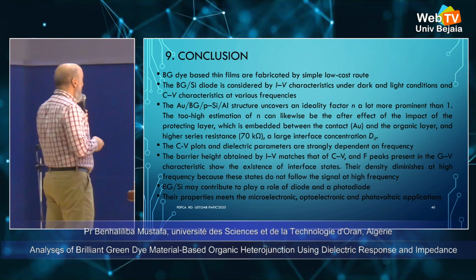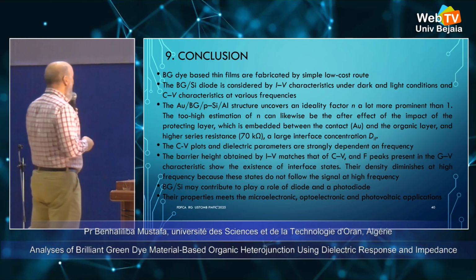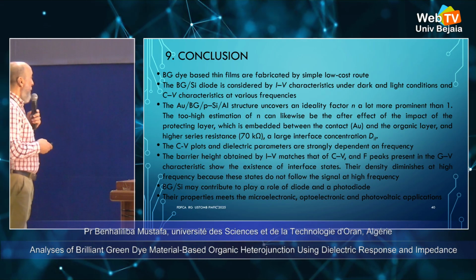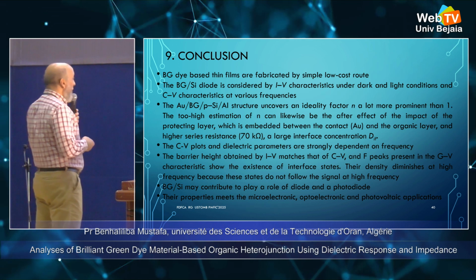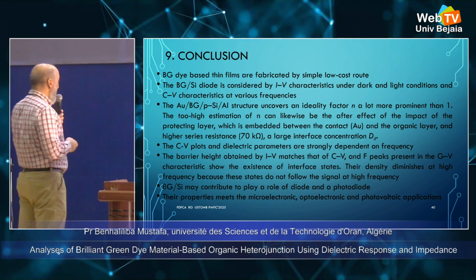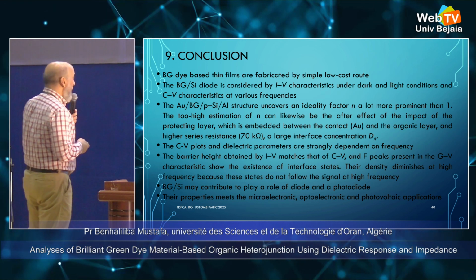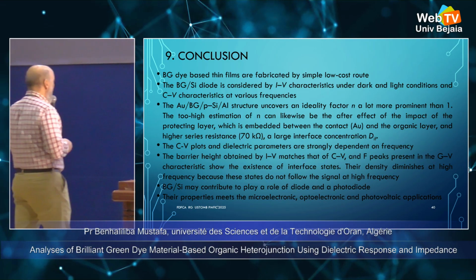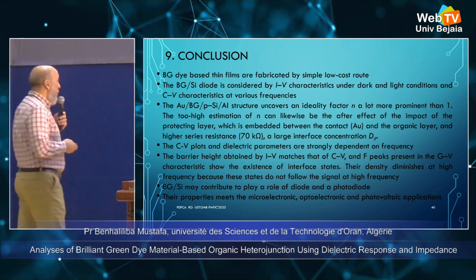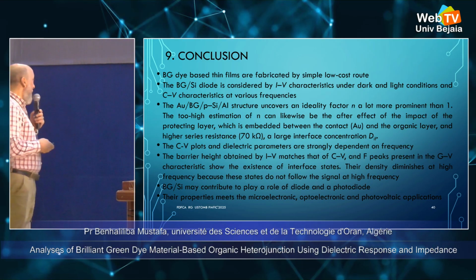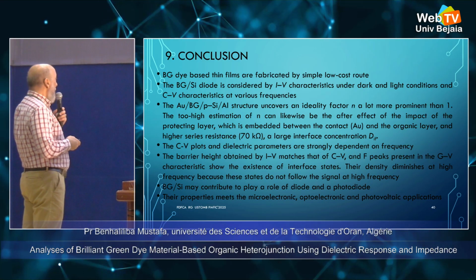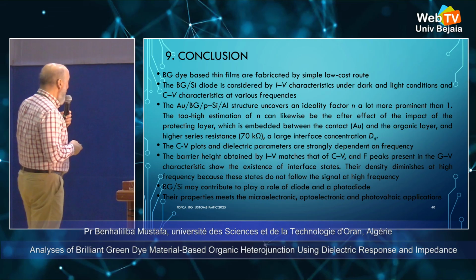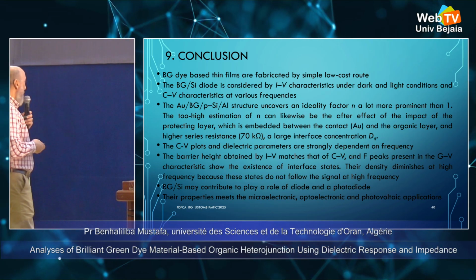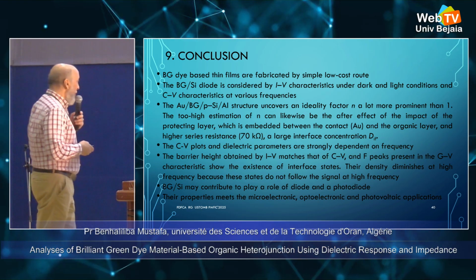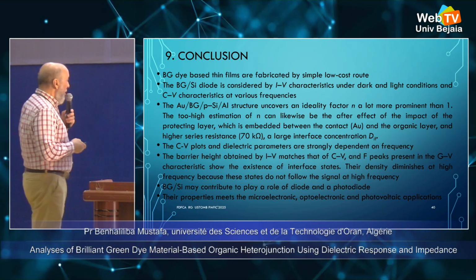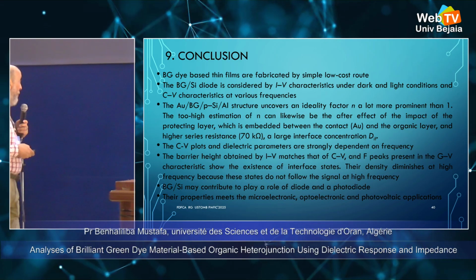The barrier height obtained by IV matches that from CV, and the peaks present in the G-V characteristic show the existence of interface states. The density decreases at high frequency because these states do not follow the signal at high frequency. BG on silicon may play the role of a diode and photodiode. Their properties meet microelectronics, optoelectronics, and photovoltaic applications.